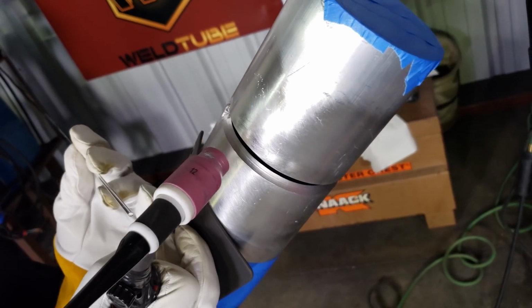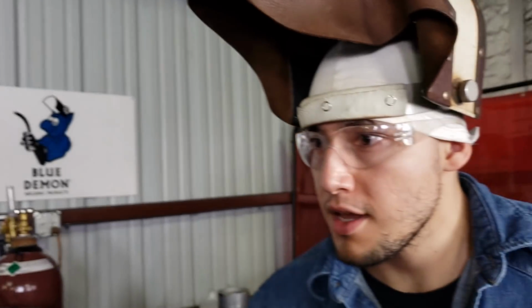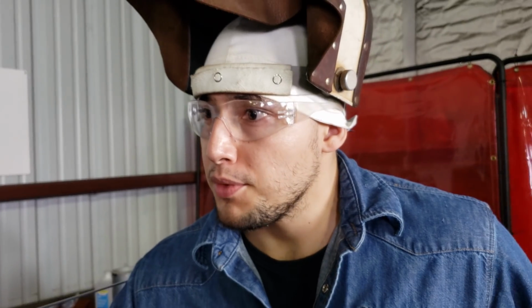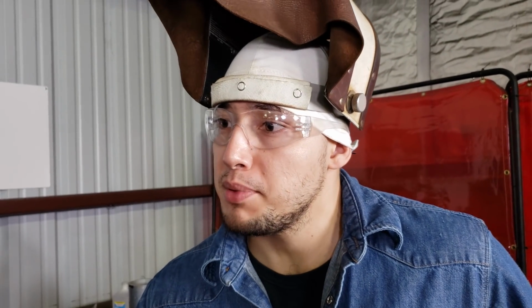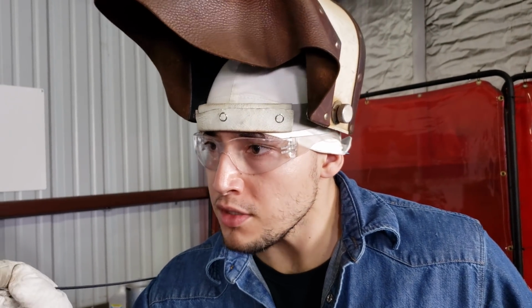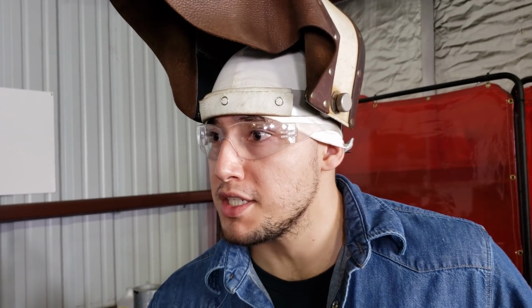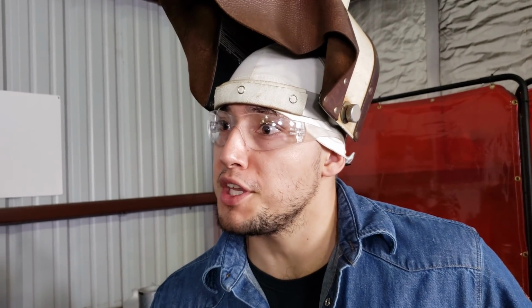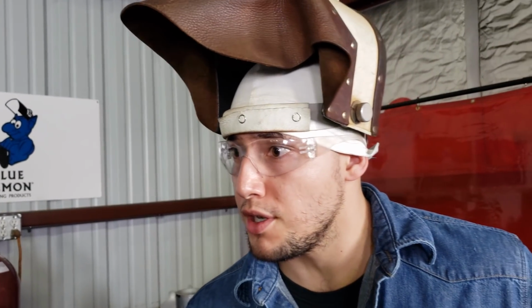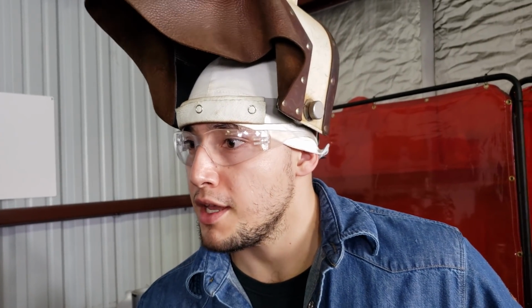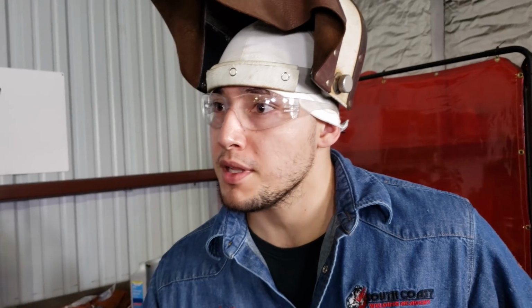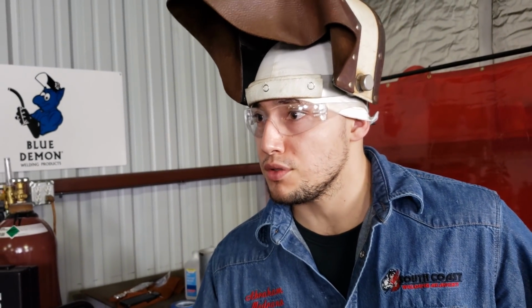Now, I have a question or something to say. For people, I know sometimes it's hard to keep the torch perpendicular. A good indication is you've got to pay attention to your keyhole. If you have a nice circular keyhole, that means you're holding the torch perpendicular. If your keyhole starts getting oval shaped, that's an indication you've got to fix your torch position.